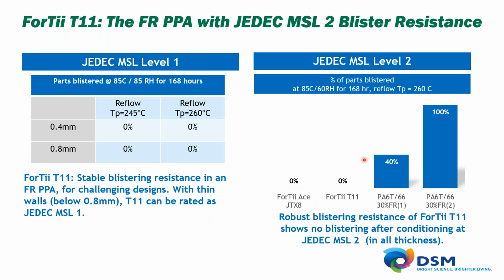Another grade that we have in the 4T family, as we mentioned, is T11. Our T11 material boasts an MSL level 2 rating at greater than 0.8 millimeters thick. But this is your flame retardant material. So if you do need the V0 flame retardant performance, 4T T11 may be a good candidate. It does have an MSL level 1 rating actually below 0.8 millimeters. So in thin parts, it is good for MSL level 1. In thicker parts, it's rated an MSL level 2 for blistering. And that's still better than most of the PPA family products out there. You can see zero tendency to blister as opposed to some of today's PPA materials.